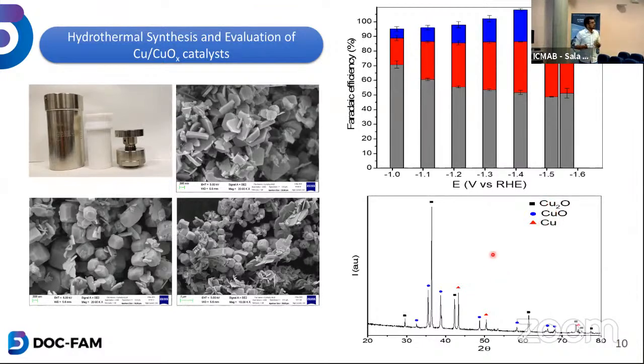Apparently Cu2O, the copper 1 oxidation state, is found to be very good for ethylene. And also, of course, copper 1 is good for other products. So when we have seen initially at lower voltages, we have a very high amount of CO, but then as I was sweeping more towards the negative potentials, towards the cathodic potentials, I have increasing amounts of ethylene, almost averaging 30% of ethylene. That's quite a good amount, or I can say a decent amount.